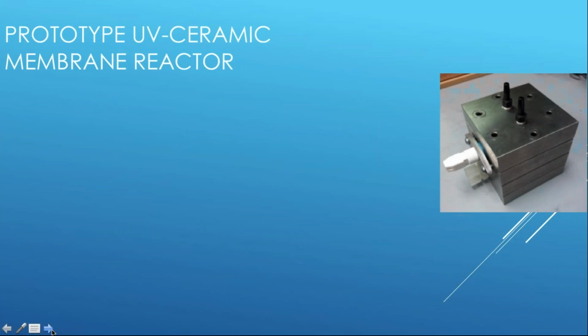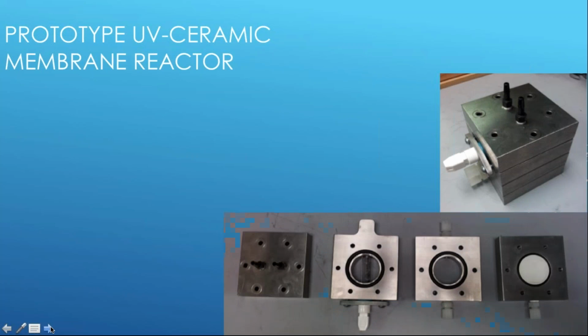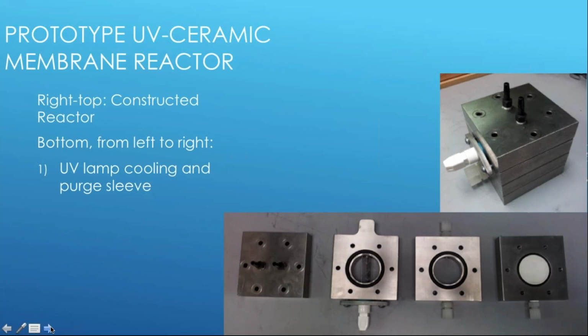And so when we initially created the bench scale, it wasn't exactly as we had envisioned, but we wanted to test the technology, and we wanted to determine if there were additional benefits of having one single unit process. Essentially what we had at the beginning was just a hunk of solid stainless steel split into 4 sections. All the way on the left-hand side at the bottom of the screen, you'll see a UV lamp cooling sleeve. This section was just to, if we wanted to, provide a heat exchange for the UV lamp. 2, we also had a UV lamp mount, and the 3rd section was the reactor cell.